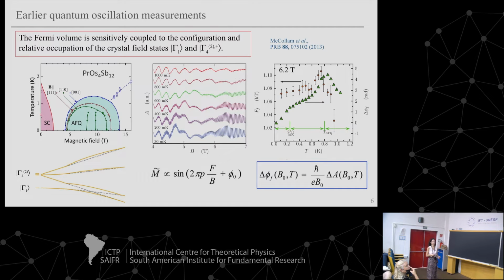You could imagine this change is probably just related to the temperature dependence of the exchange splitting of the Fermi surface. As you mix this singlet and magnetic triplet levels, you're mixing a magnetic state into the ground state. So you're increasing the magnetization and you're increasing the exchange splitting of the Fermi surface. But this should saturate. So we didn't really know why it suddenly got more temperature dependent, that this was enhanced.